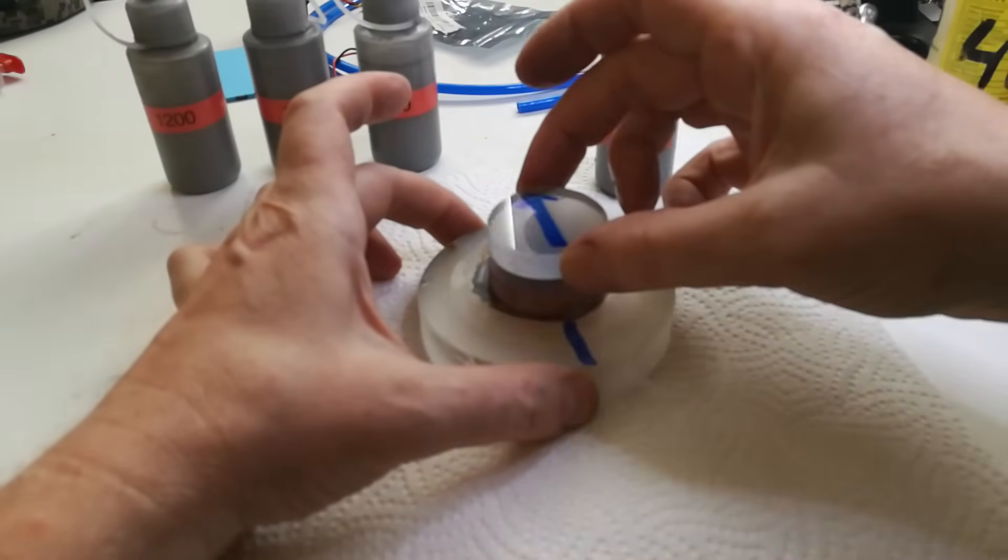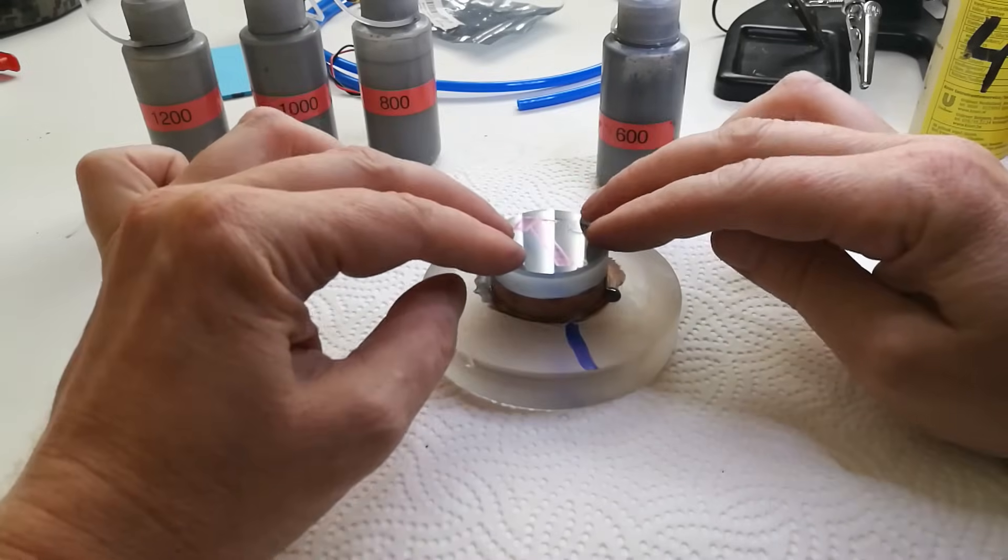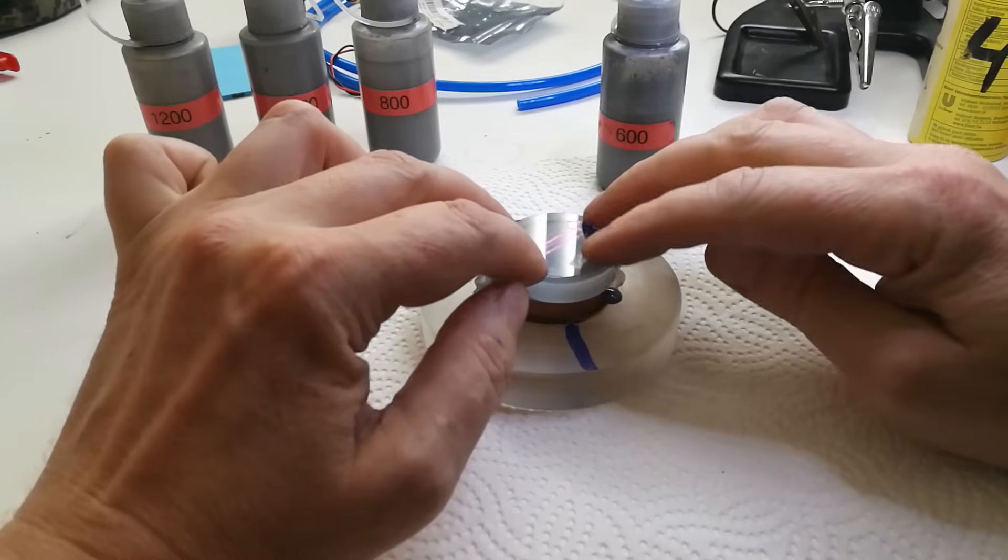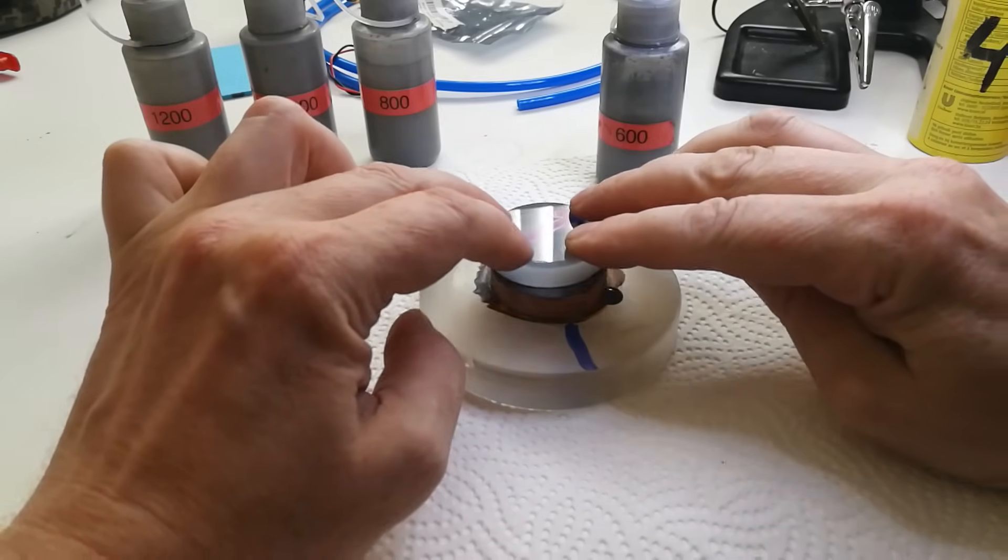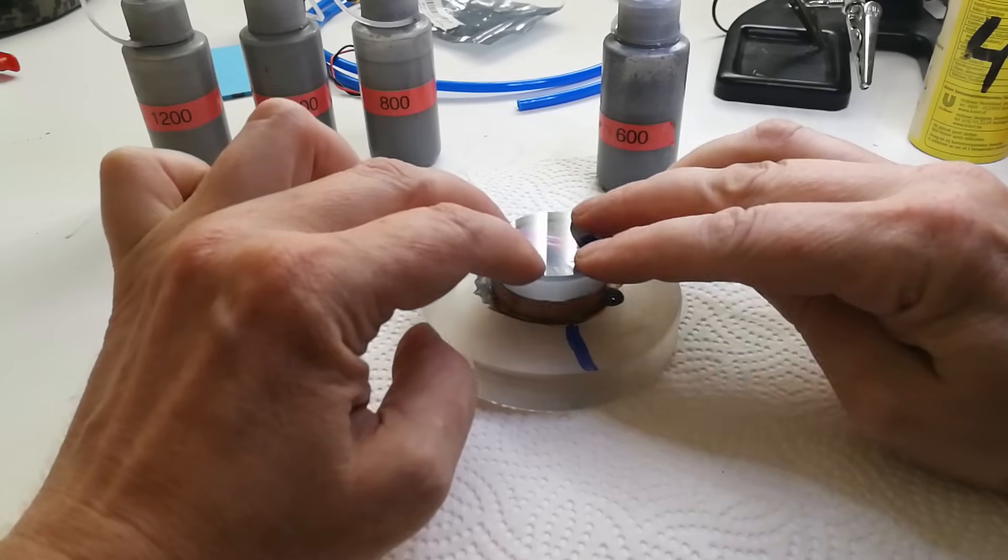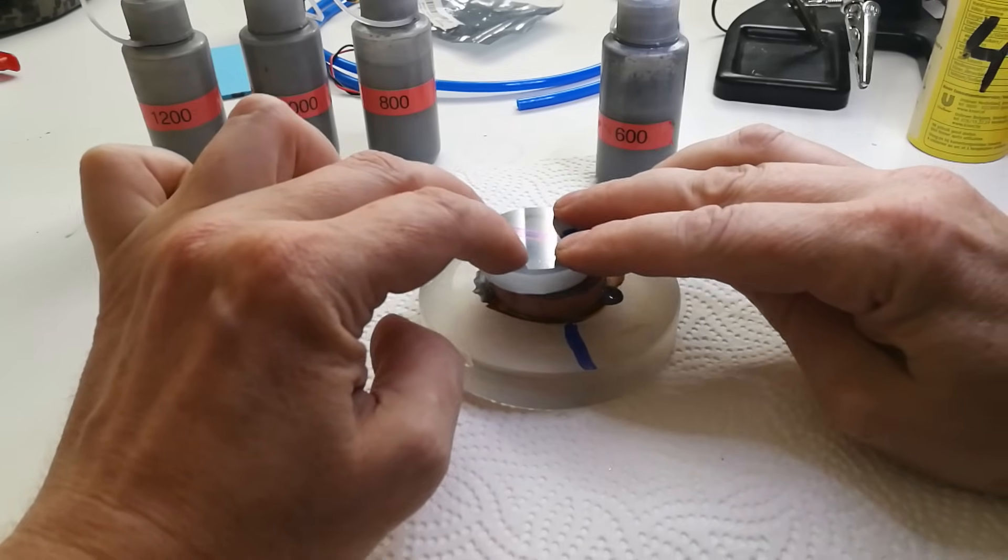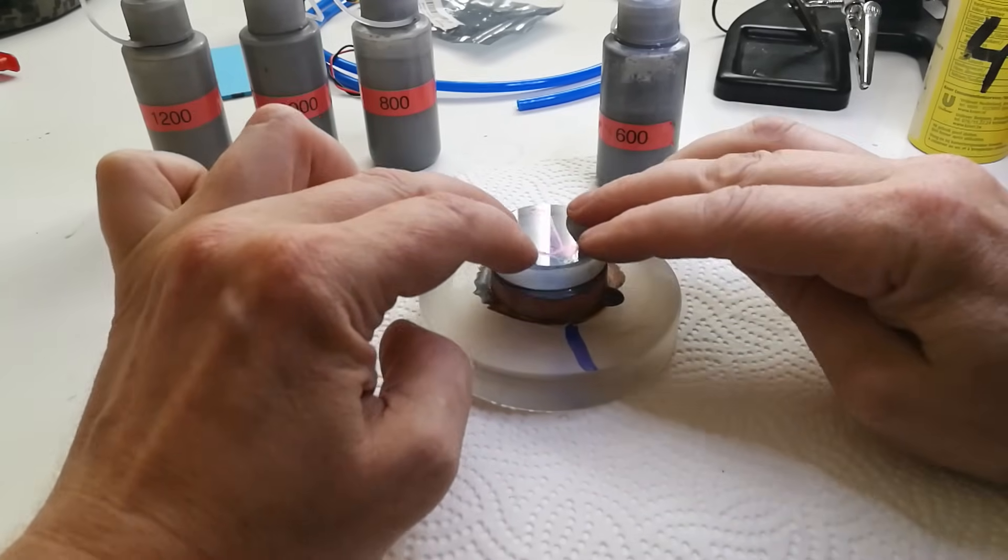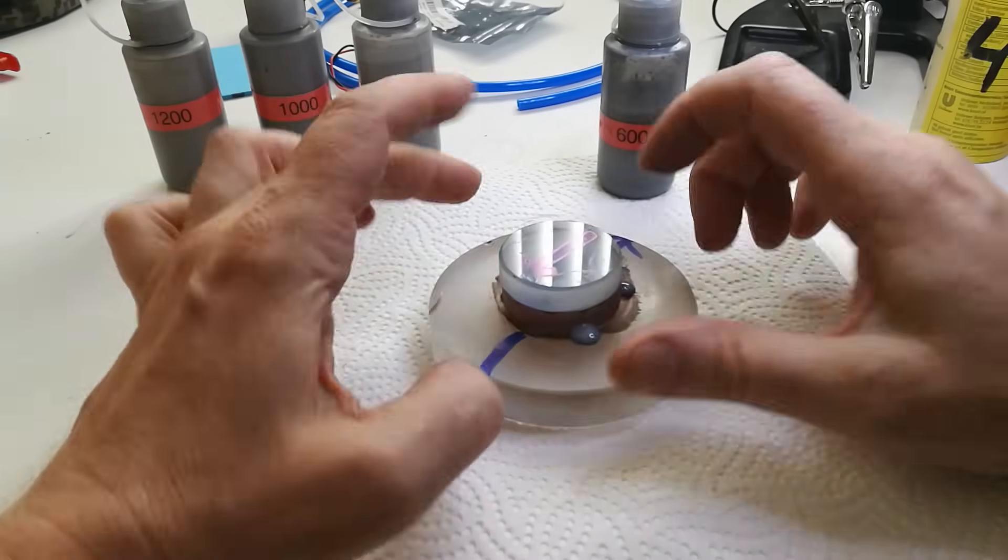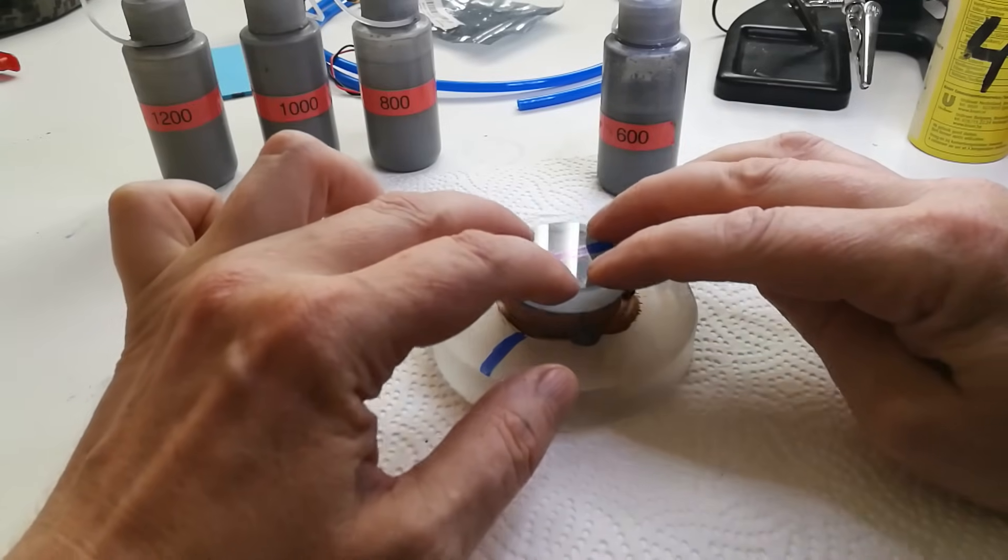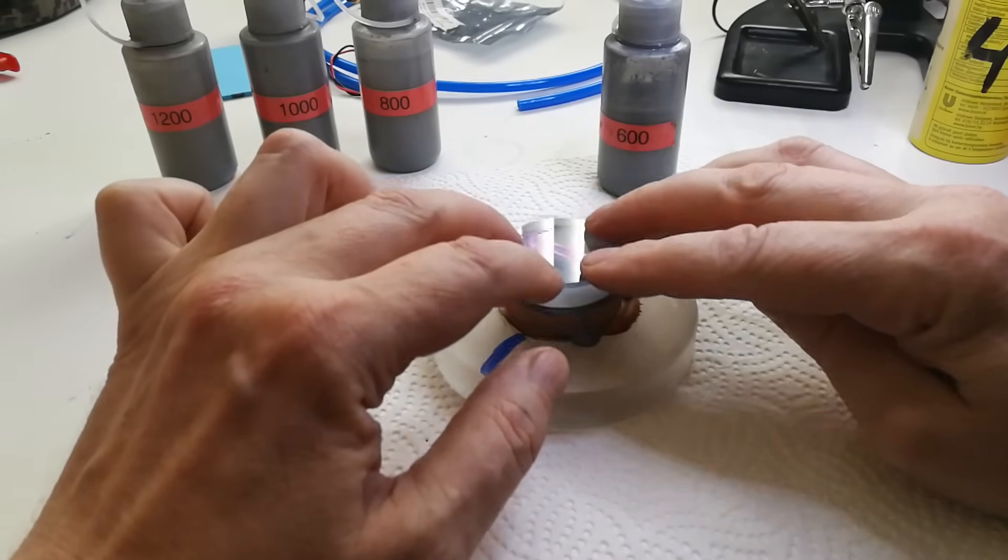There are several ways you can grind the surface to a good spherical shape. Basically all methods involve the constant rotation of the blank and the tool in order to prevent grinding over one specific direction too long. So if you grind over the same direction all the time, the surfaces will gradually become cylindrical instead of spherical. So it is vital to rotate the blank and the tool very regularly and at different rates or even directions in order to end up with a nice spherical shape.